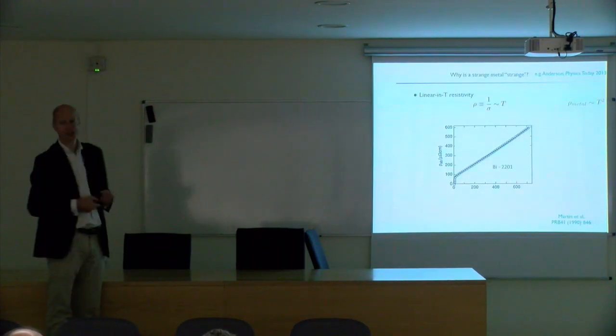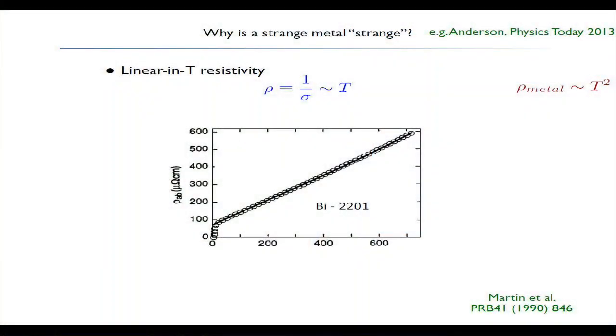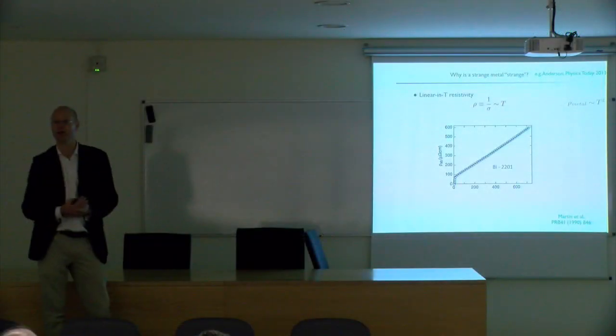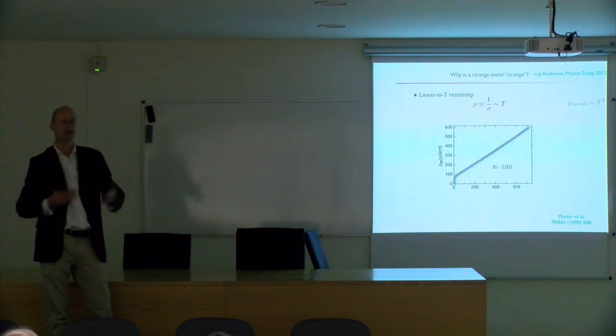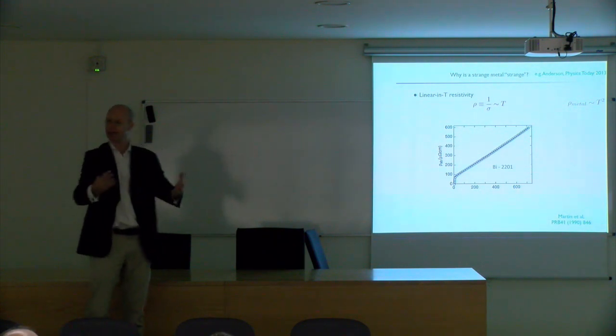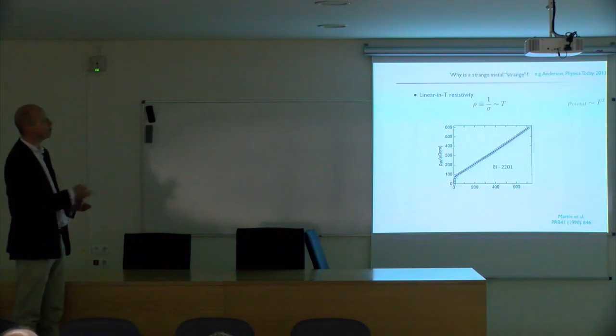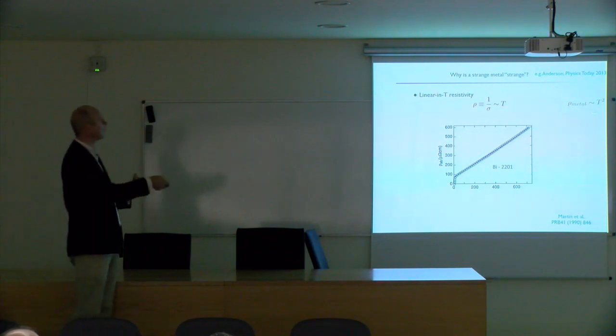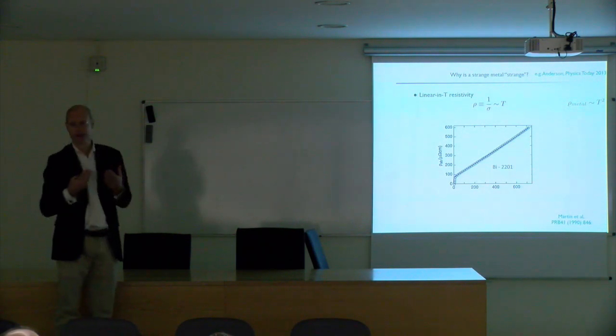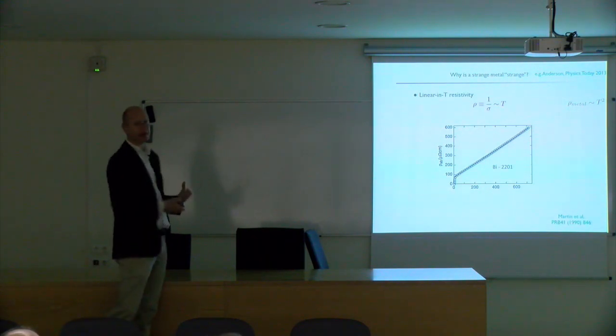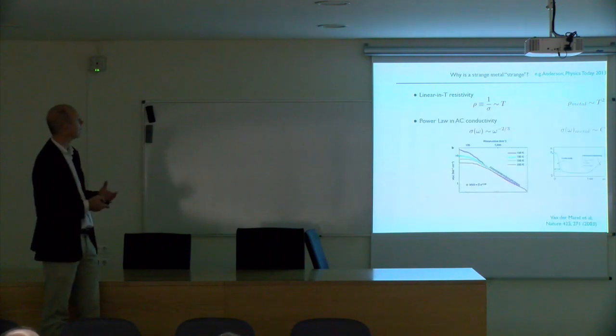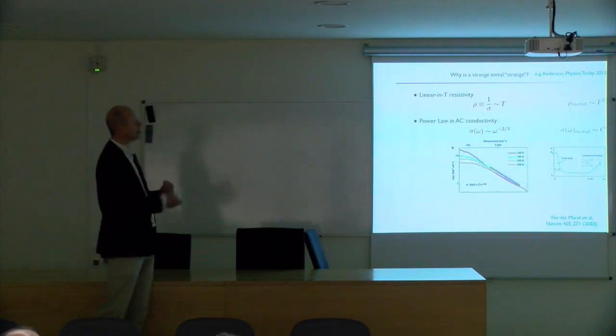Well, one is that if you look at the resistivity as a function of the temperature, it scales linearly with the temperature. Here is some early data from the 90s. Here you see the resistivity. This is the temperature scale, and you see it is almost a perfect straight line all the way down to the onset of superconductivity, that is this big jump here. And this is very strange, because in ordinary metals, like I said, we know exactly how to compute these things. We take our electrons, these electrons scatter. That scattering causes some friction. This friction is the effective cause of the resistivity. And if you compute this in ordinary metals at low enough temperatures, you can compute that it scales as the temperature squared, not as the temperature. So this is really a big difference between these two metallic systems.